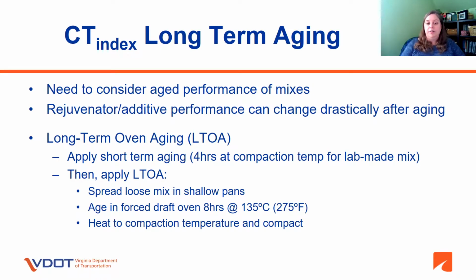To apply the long-term oven aging, you'll spread the loose mix in a shallow pan. The thickness of that loose mix should be roughly your nominal maximum aggregate size. Age the mix in a forced draft oven for 8 hours at 135 C or 275 Fahrenheit. Then reheat to compaction temperature and compact.